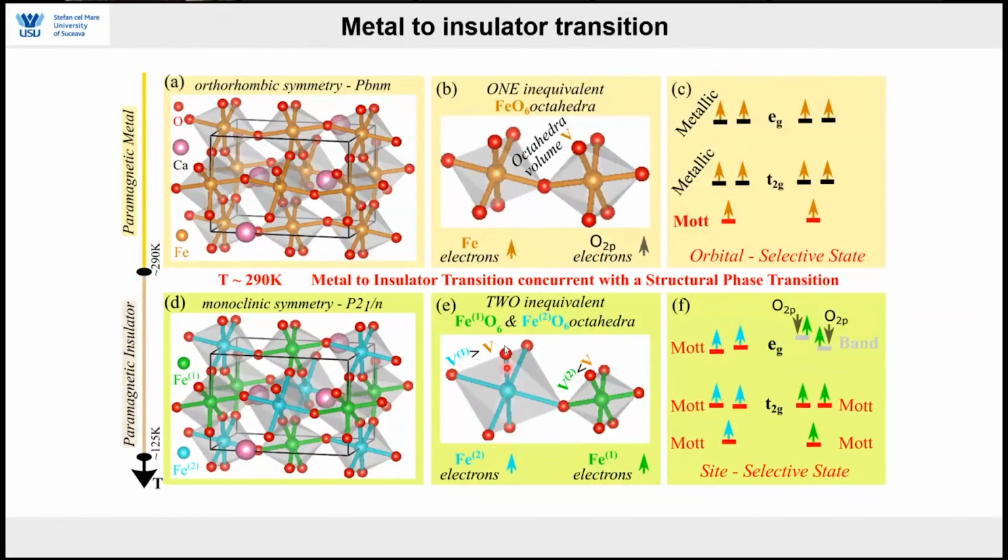Okay, so I will go quickly through. So this last material, the idea was, again, you have charge order. Experimentally, what's happening is you have a metal to insulator transition without magnetic ordering. Again, at high temperature, you have iron inside of octahedra. All the octahedra are identical. You lower the temperature, and you have one octahedra expanded, one octahedra contracted, in terms of the crystal structure.